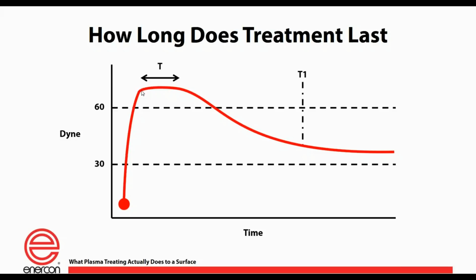Well, how long does it last? Well, that's based on a number of questions. First, it's going to steady state for a time t. Now, t is going to depend mostly on the material and the method in which you treat it. For plastic, sometimes you may have 4 to 24 hours. For some metals, you may have 18 to 48 hours. I've had some carbon fibers that have lasted for weeks. So time t just varies on the surface, and you have to basically run this test to figure out what that is. Then after that time t, you're going to start seeing a degrading effect over time.